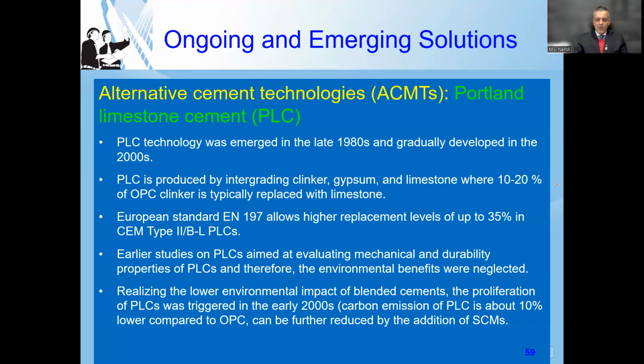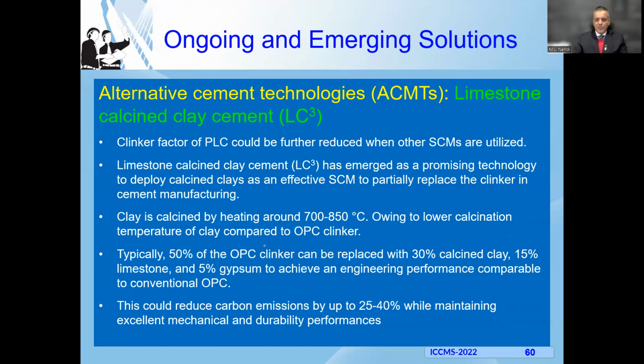Now we can use PLC cements, maybe containing somewhere around 10, most commonly 10% of limestone, could be up to 20%. In the European standard, they have a cement that maybe could contain all the way around 35% of ground limestone. The earlier studies were rather focusing on the mechanical and durability features of Portland limestone cements, and later on came the perception that it actually saves CO2 emissions as well, and therefore there is more interest now in using these types of cements for sustainability purposes.